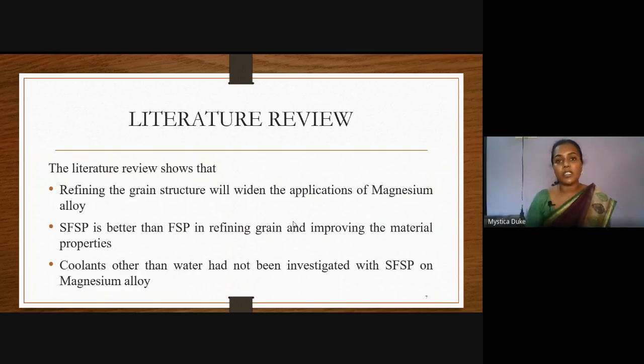So the takeaway from the literature review was, first, as I told, we saw that the magnesium alloy needs improved ductility. So we chose magnesium alloy for this study. And we found out that submerged friction stir processing is better in producing refined grains when compared to friction stir processing. So we went with submerging the friction stir processing setup. Next, we have seen that the coolants chosen so far in submerged friction stir processing are only water, and sometimes cryogenics, but they have not explored any other coolants. So we went with other coolants.